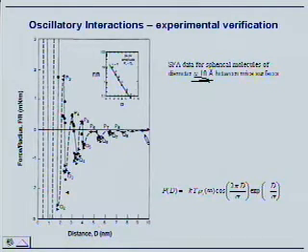So when you go less than 10 molecular diameters, you suddenly see that the force goes up, down, up, down, up, down. So suddenly, depending on where you are, if you're exactly at 1, 2, 3, 4, and so on nanometers, you have attraction. If you're at 1.5, 2.5, 3.5, 4.5, and so on, you have repulsion. And then the whole of it slightly tilts downwards here, as you can see. Well, maybe you can't see because the pen wouldn't write, but you can see that the average goes down.